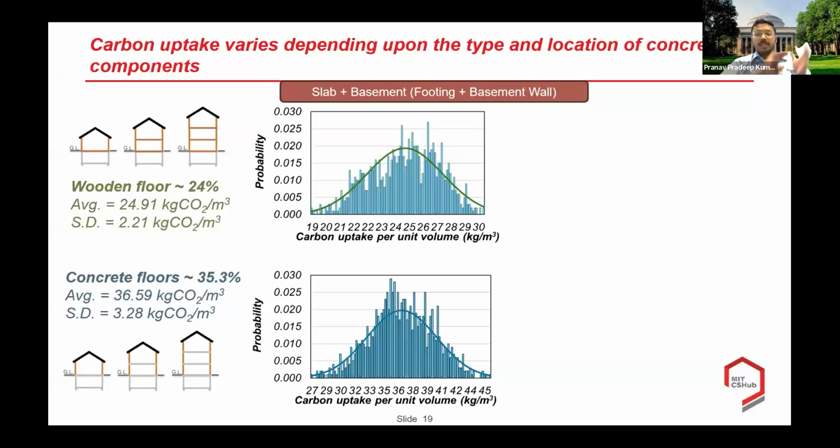So going back to the question that I had asked at the beginning as to what could approximately be the amount of calcination emissions that can be sequestered in a single family housing, we can see from this example here for the single family housing that it has a potential to absorb approximately 20 to 40% of the calcination emissions over its entire life cycle or the use phase stage.